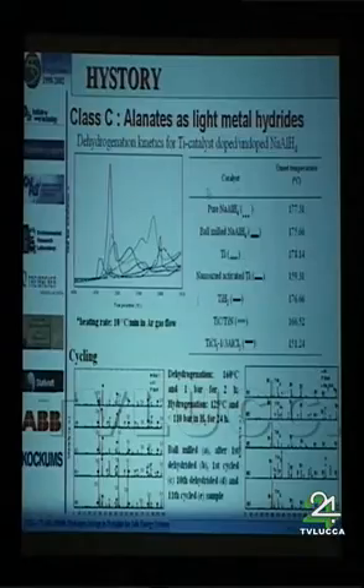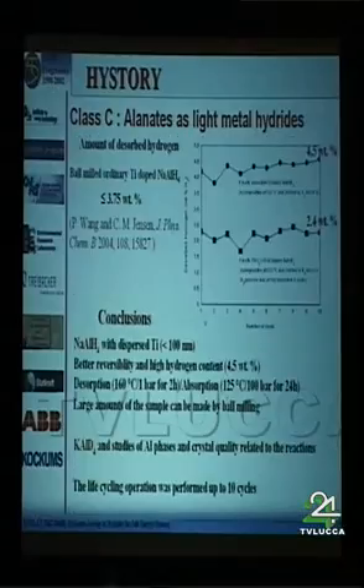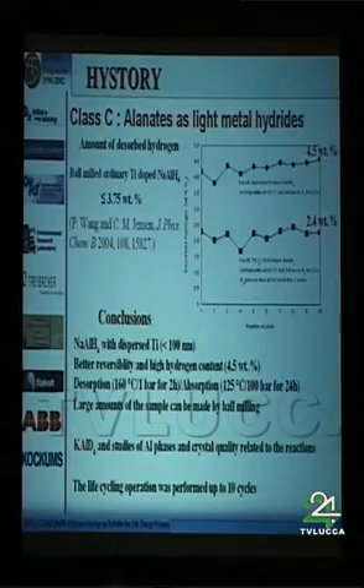The most interesting progress has been made by using a special type of titanium catalyst, in consideration of the many catalysts already known and used in many groups in the world. Nano-sized activated titanium appears to be probably the best metal catalyst we can use to activate sodium alanate. For example, in terms of cyclability, it is possible to deliver about 4.5 weight% of hydrogen after 10 absorption-desorption cycles, compared to what is known from literature using ordinary titanium powder.